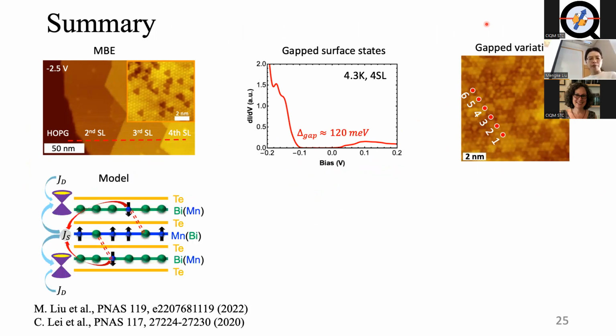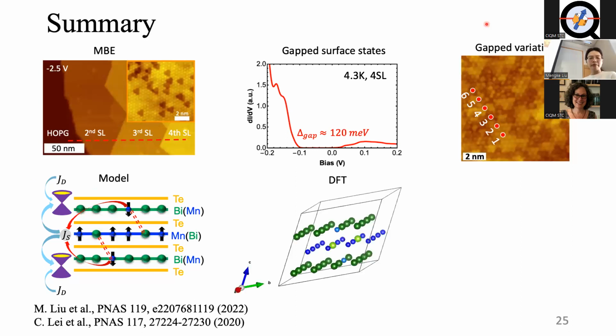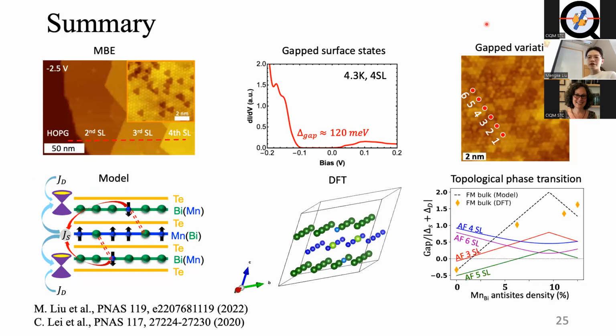Okay, so we used a coupled Dirac model to account for those defects. And we combine the coupled Dirac model with the DFT calculation, and then we provide an understanding of the topological phase transition, why it's so sensitive to anti-site defects, and why people did not observe the quantum anomalous Hall effect universally in the field.